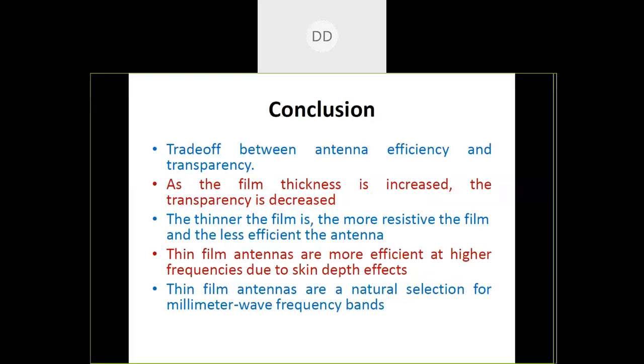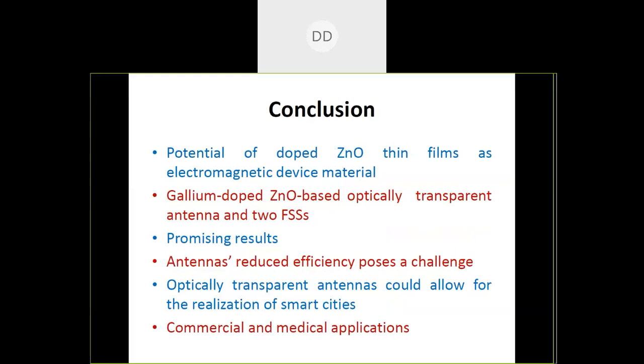Also, we have observed that thin film antennas are more efficient at higher frequencies due to skin depth effects. So the thin film antennas are natural selections for higher frequency ranges which are going to be used in 5G communication. And we have also discussed the potential of this gallium doped zinc oxide based thin film for designing antennas and optically transparent filters or frequency selective surfaces. So what we have seen is that promising results are there, but challenges also exist. So if we want to design these optically transparent antennas, then we researchers must overcome these challenges.